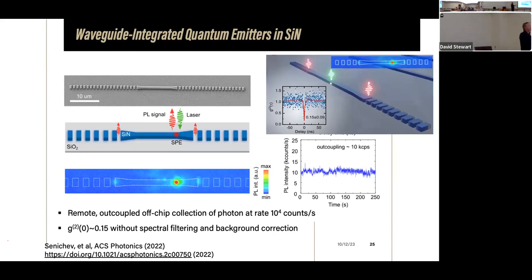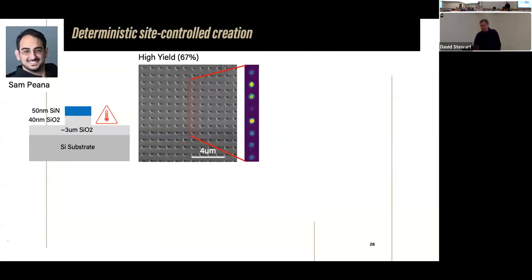And we obtain that the g2 coming from this emitter is still quite low and good, high purity. By the way, this is again room temperature measurements. Stability is good, nothing happened this time. So that clearly indicates that we could successfully couple these single photon emitters to a waveguide.